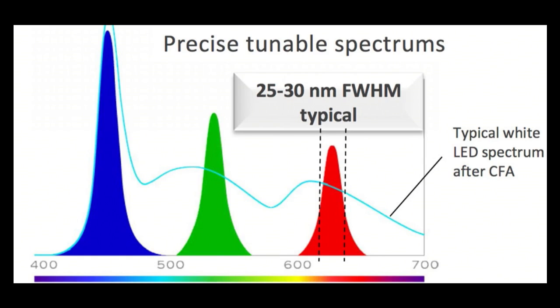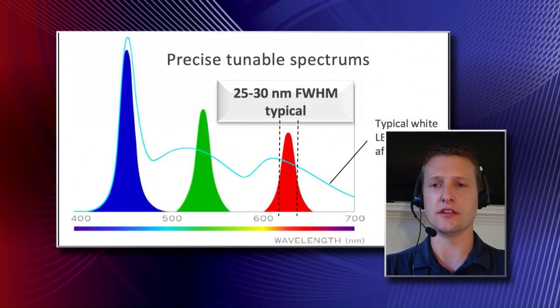Right. So the blue in both cases is coming directly from a blue LED. And in the quantum dot case, the red and green is coming from absorbing that blue photon and converting it into either a red or a green. In the overlay there, what you're looking at is a white LED, which is really a blue LED with a broad phosphor that emits all across the visible. But then with the filters involved as well, which filters out the light and gives you semi-pure greens and reds, but clearly not nearly as good as the quantum dots can do.